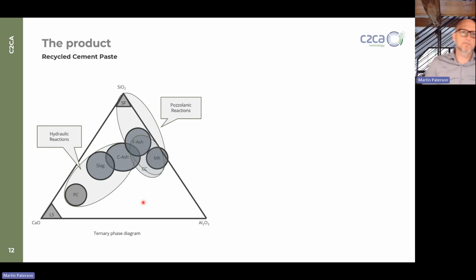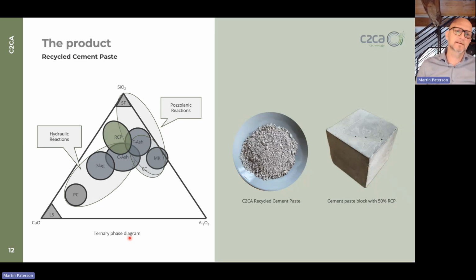A little bit more in detail about the product. So you see the ternary phase diagram here. Since our material is semi-hydraulic and semi-pozzolanic, it's located somewhere in the middle, and that's how it looks as a powder and within a concrete block, where we used 50% of that material.